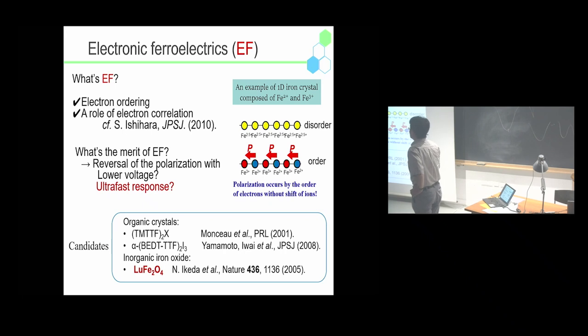The next point is, what is the important merit of the electronic ferroelectrics? In electronic ferroelectrics, electrons can play an important role rather than ions or atoms. The electrons are even lighter than the atoms, so we can easily change the polarization with a lower voltage and with ultrafast response. Those are the merits of the electronic ferroelectrics. Based on these respects, several candidates for electronic ferroelectrics have been proposed: organic crystals such as (TMTTF)2X and alpha-(BEDT-TTF)2I3, and Professor Ikeda proposed the LuFe2O4 as an electronic ferroelectric. Today, I'd like to talk about these materials.